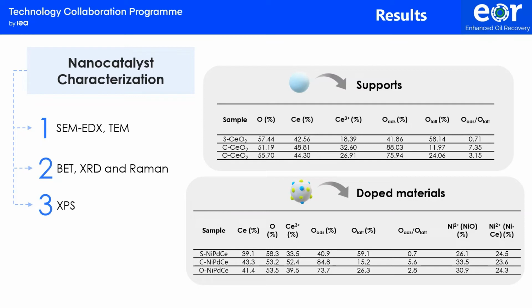Interestingly, the amount of ceria 3+ ions increases with nickel and palladium functionalization in all samples. The increase in ceria 3+ proportion, ranked as spherical lower than orthorhombic lower than cubic, may reflect the surface modification of oxygen vacancies after metal loading.